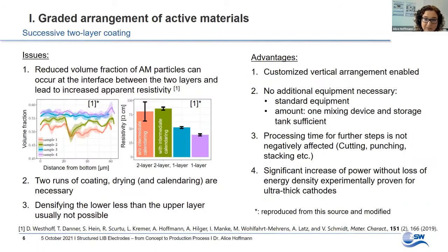But there are also some issues associated with the successive two-layer coating. By combination of experiments and simulation, it was found that the volume fraction of active material particles can be reduced at the interface between the two layers, probably especially in the case of intermediate calendering, and that this can lead to an increased resistivity. Furthermore, the method implies two runs of coating and drying, and the graded arrangement of porosity can usually only be realized for the case of higher density near the current collector and not vice versa.